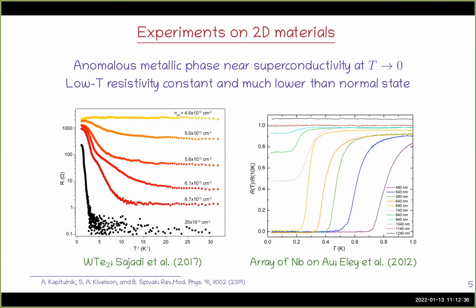I have probably a very naive comment on this. I'm aware of this, and it's true that these are very complicated experiments, and there could be some subtle heating effects and some substrate effects or connection effects and so on. But as far as I know, and I'm taking the word of the experimentalists on this, which I also learned from the review article that I cite here, at least in these experiments people have carefully checked the effects of heating and the connections and so on. And they are quite sure that this is really the true effect. And recently we also had talks from Aharon Kapitulnik, who was visiting here, and he also showed some new data on these critical phases, which I don't show here right now. But he had some recent experiments again on this anomalous metal, and it seems to be there ubiquitously despite different checks.